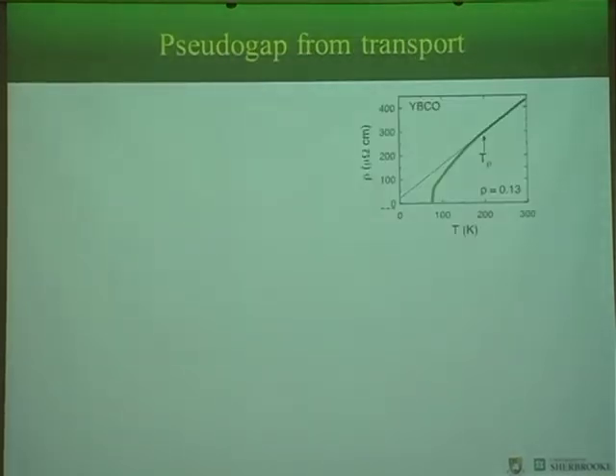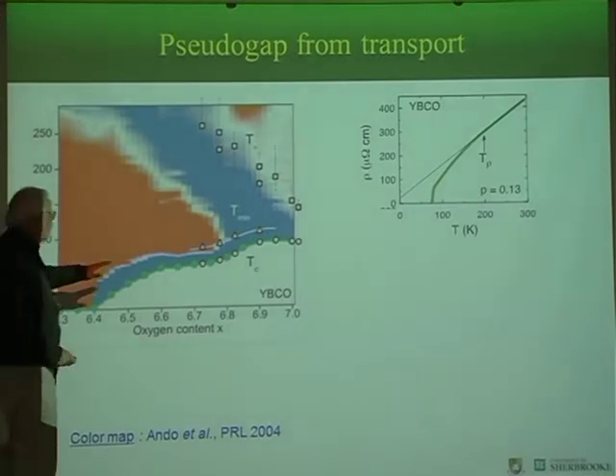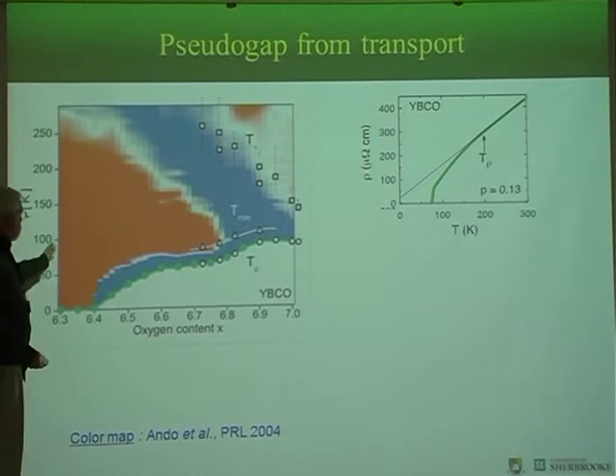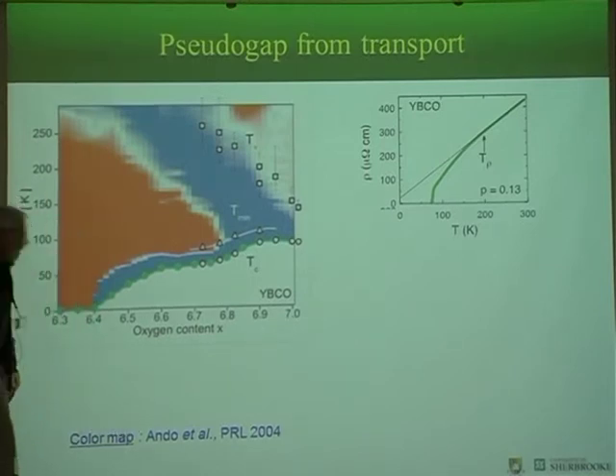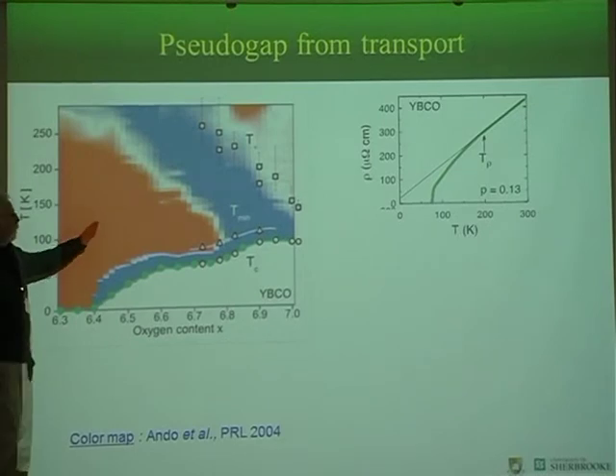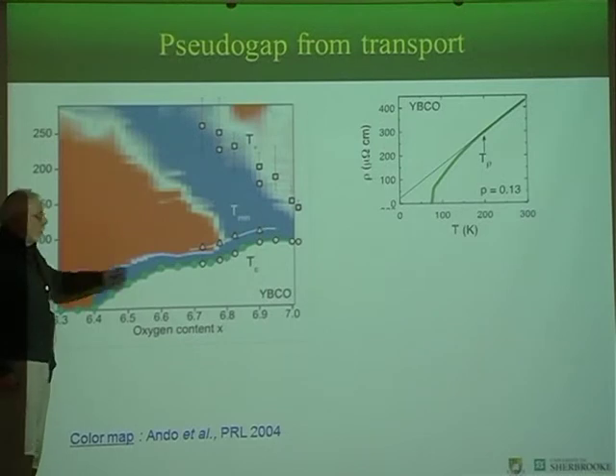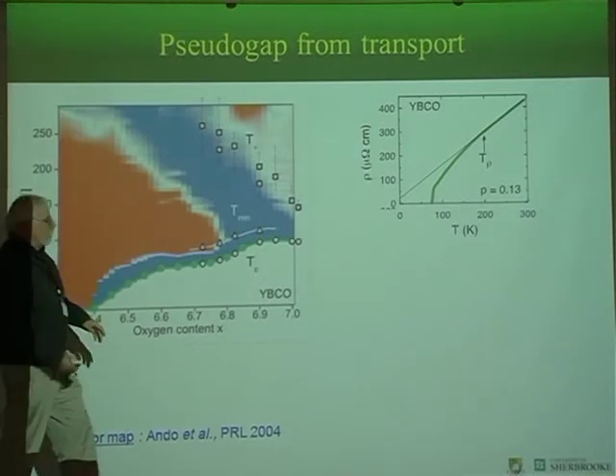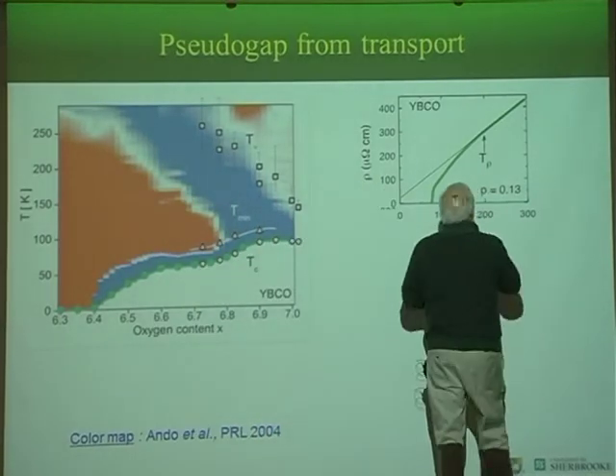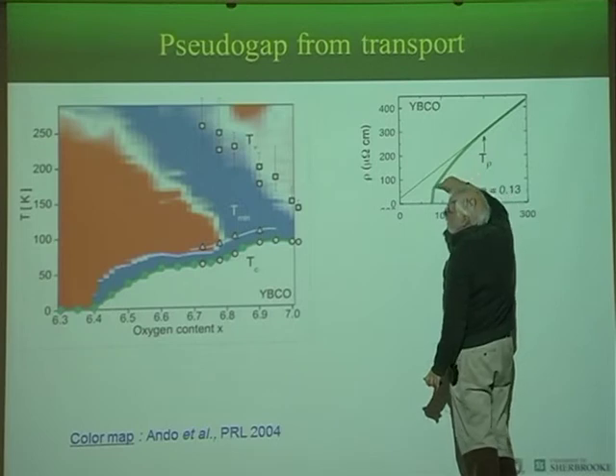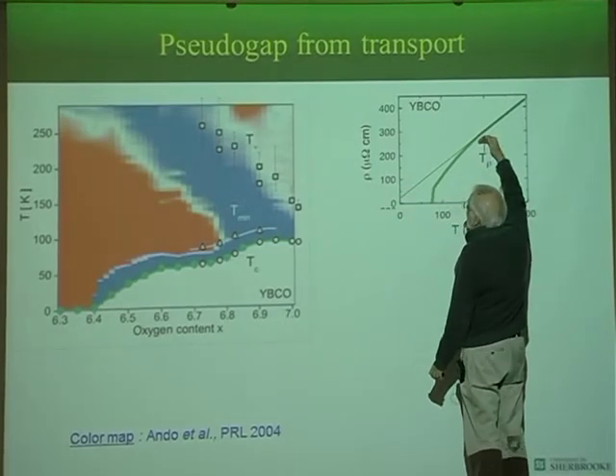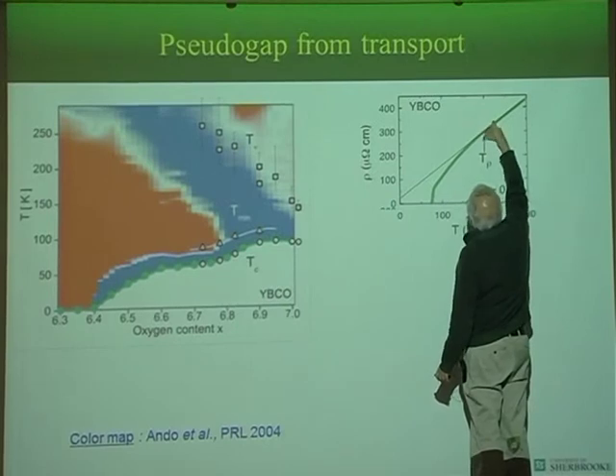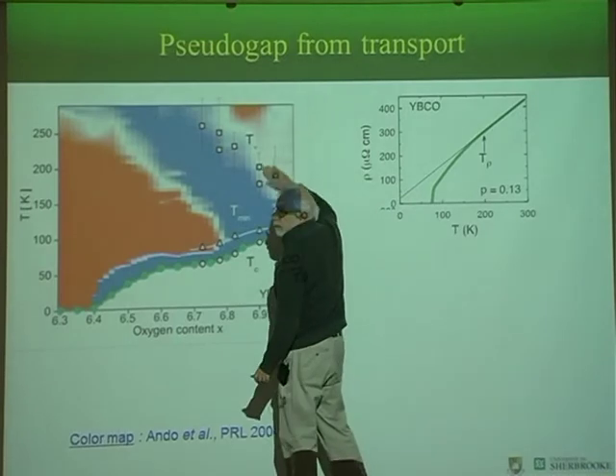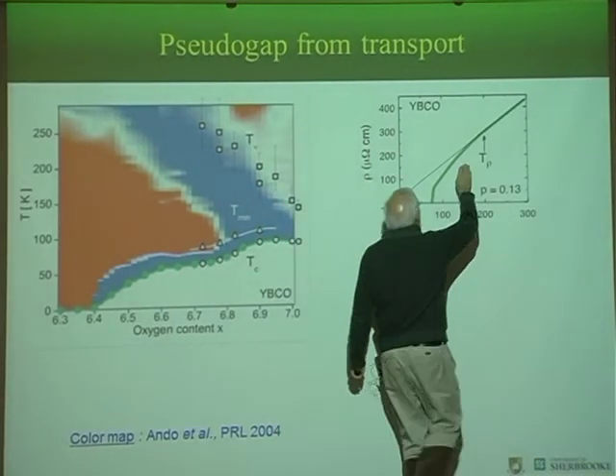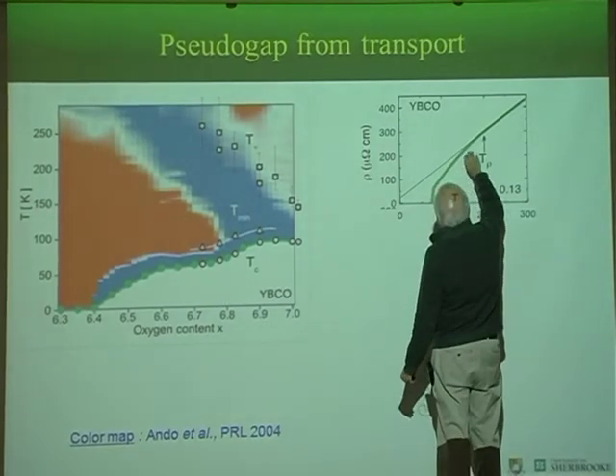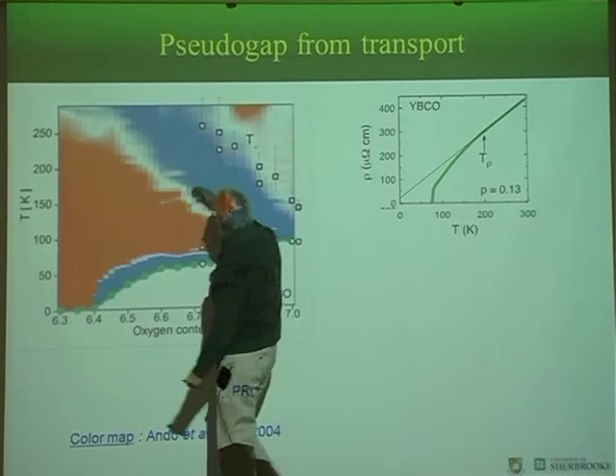Okay. Now, this pseudogap temperature was seen also in transport measurements. So this is a plot of data by Ando. And what is plotted here is the second derivative of the resistivity at every temperature. So you take a curve here, resistivity as a function of temperature. At every point, you compute the second derivative, and you make a color plot. And people call the pseudogap this deviation from linearity. Linearity here means white. Second derivative is 0. And then it curves like this, and then the other way. So it changes from blue to red.